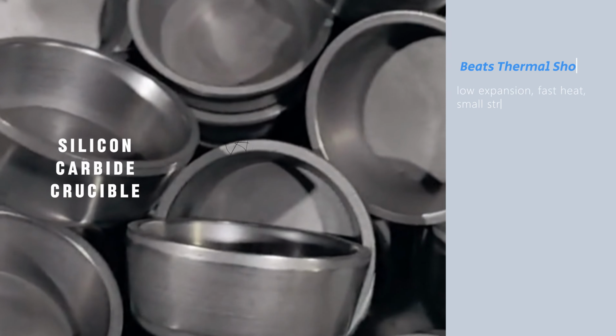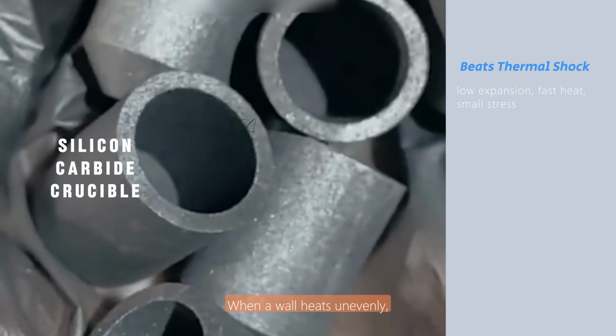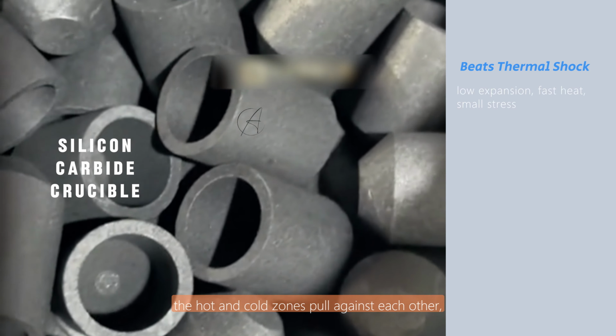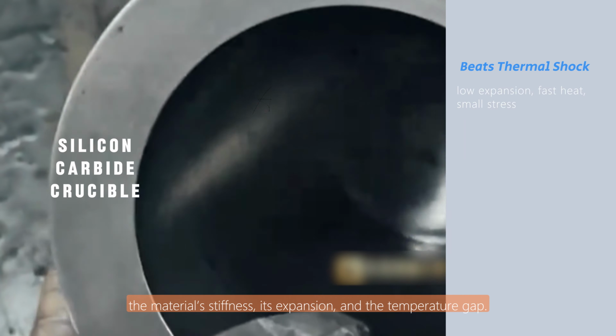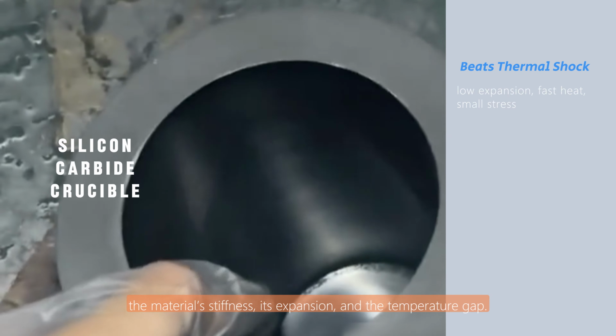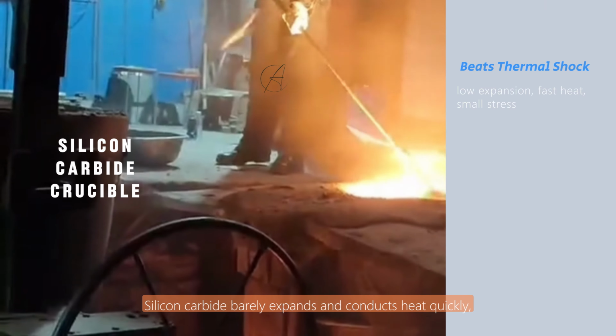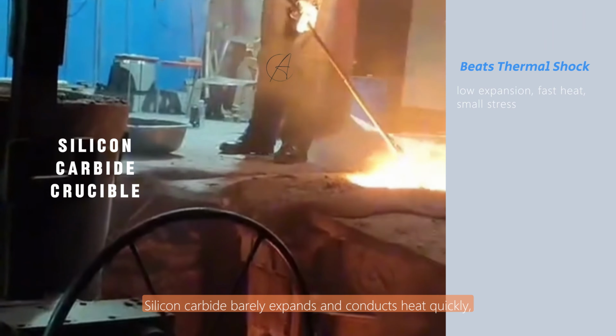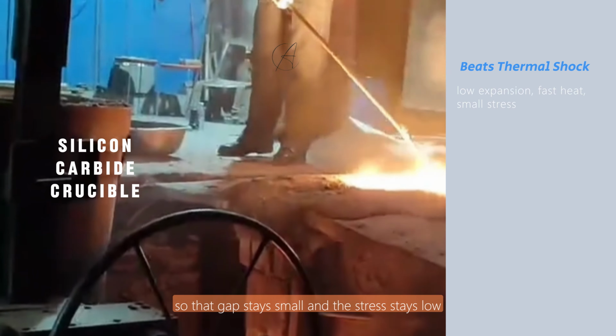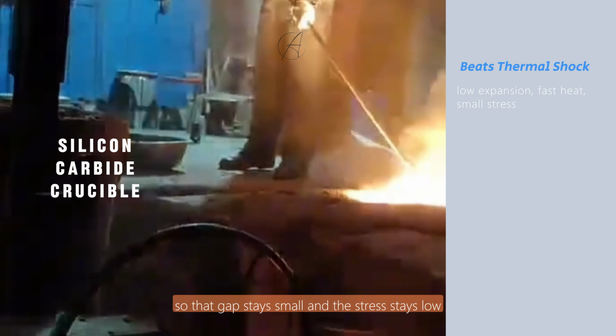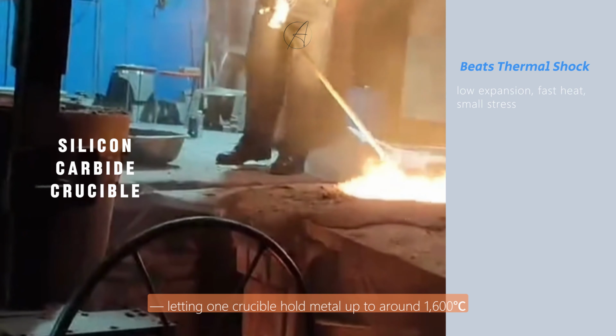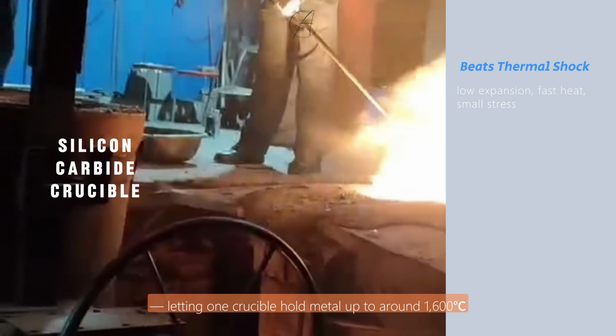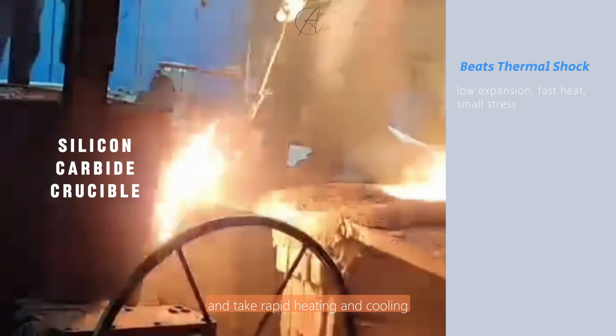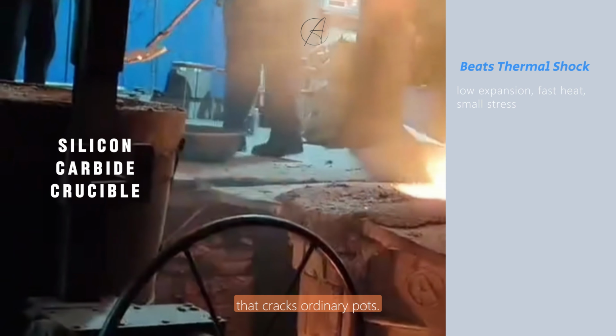Surviving the furnace is really about thermal stress. When a wall heats unevenly, the hot and cold zones pull against each other, and the stress rises with the material's stiffness, its expansion, and the temperature gap. Silicon carbide barely expands and conducts heat quickly, so that gap stays small and the stress stays low. Letting one crucible hold metal up to around 1600 degrees and take rapid heating and cooling that cracks ordinary pots.